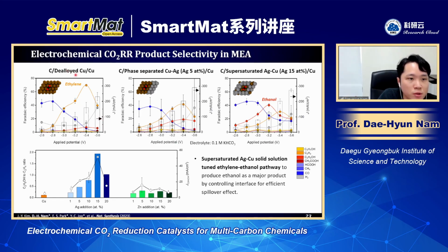So in the case of the dealloyed copper, it means that there is no silver in it. The x-axis shows the potential, the left-hand side y-axis shows the Faradaic efficiency, and the right-hand side y-axis shows the current density. As you can see, as we increase the potential, at the low potential range, we can see the existence of some CO. And if we keep increasing the potential, we can see the decrease of the CO, and this decreased CO contributes to the increase of ethylene. It means that in dealloyed copper, the major product is ethylene, the hydrocarbon one.